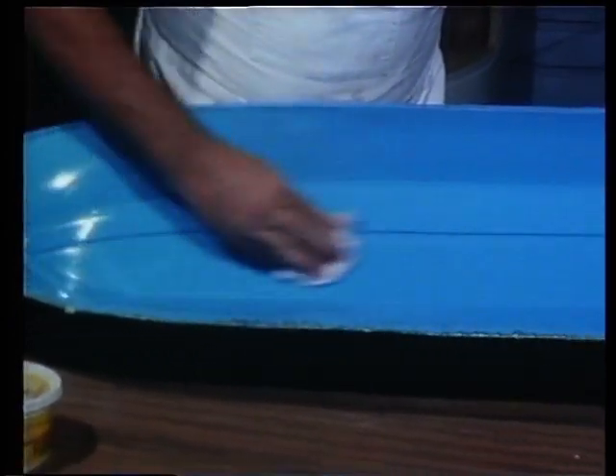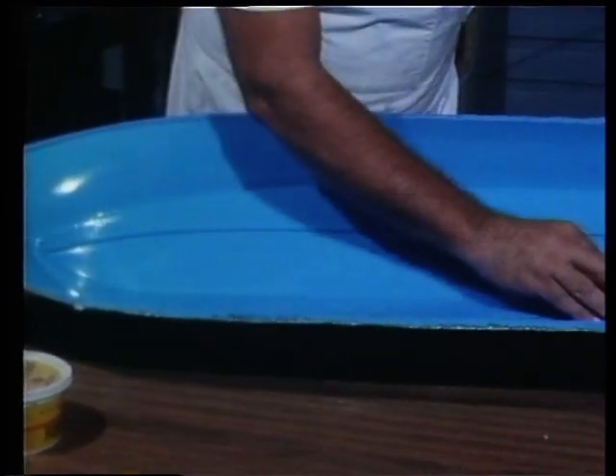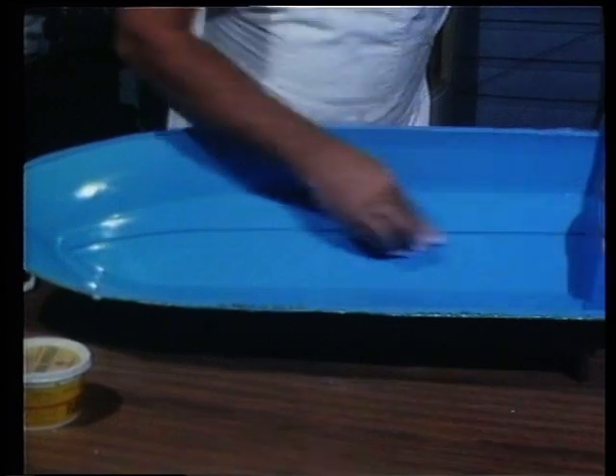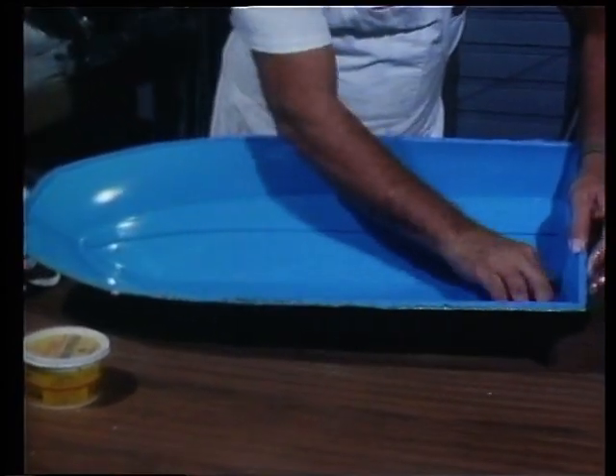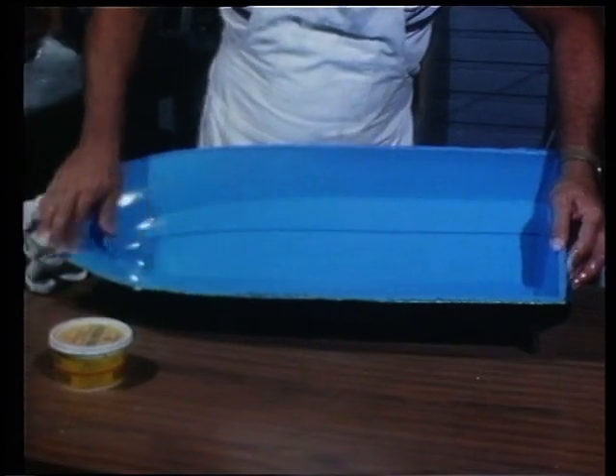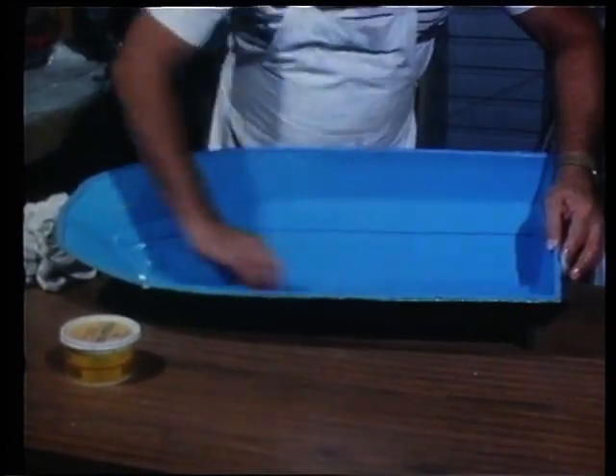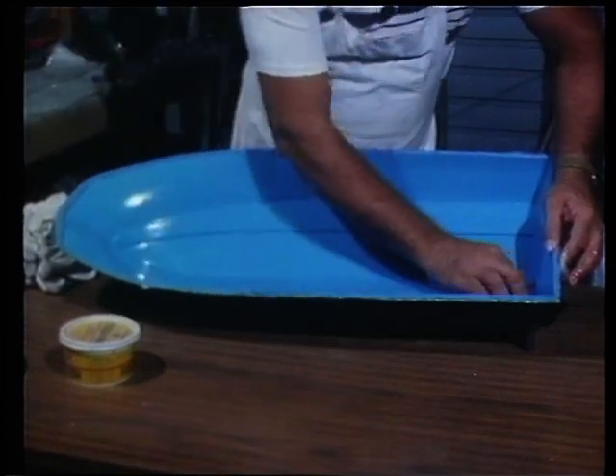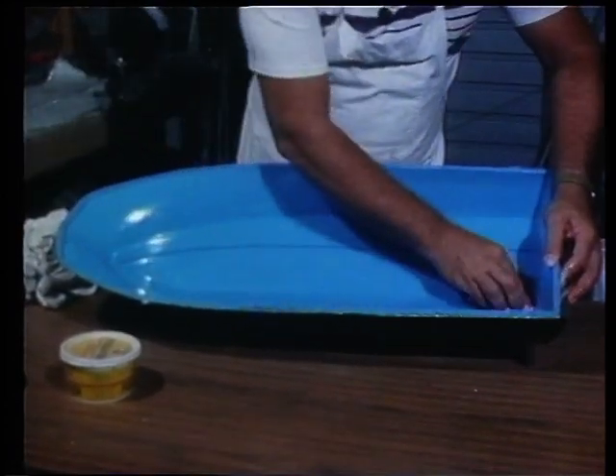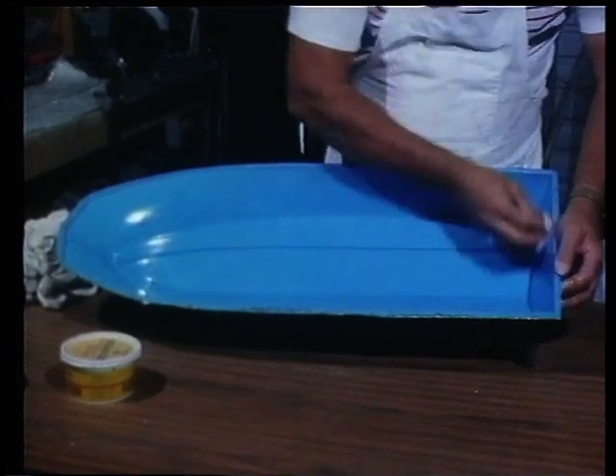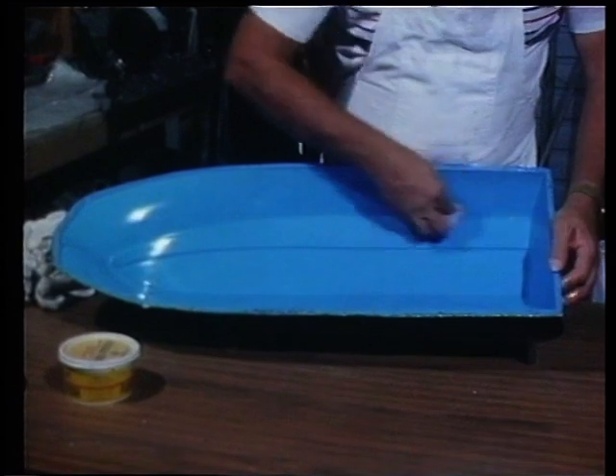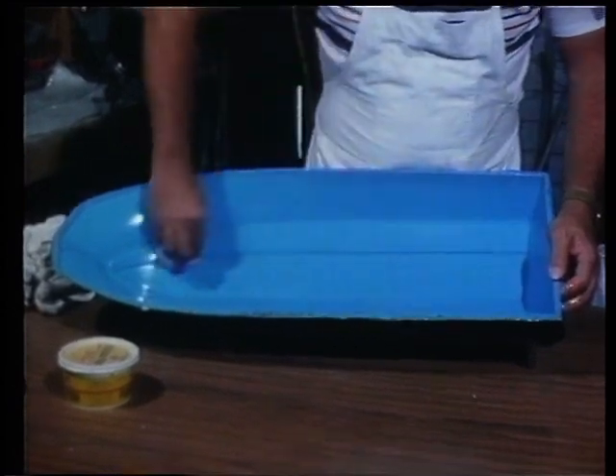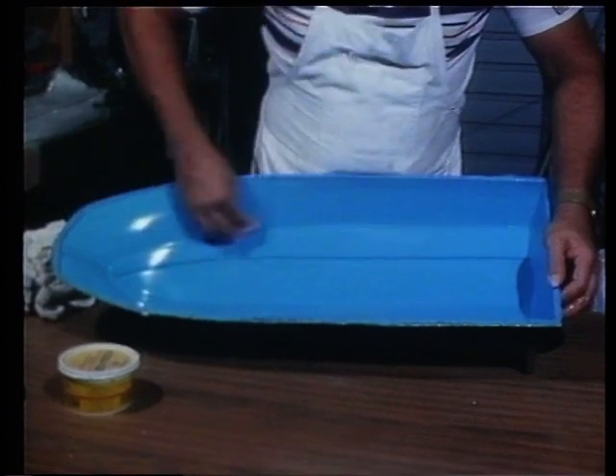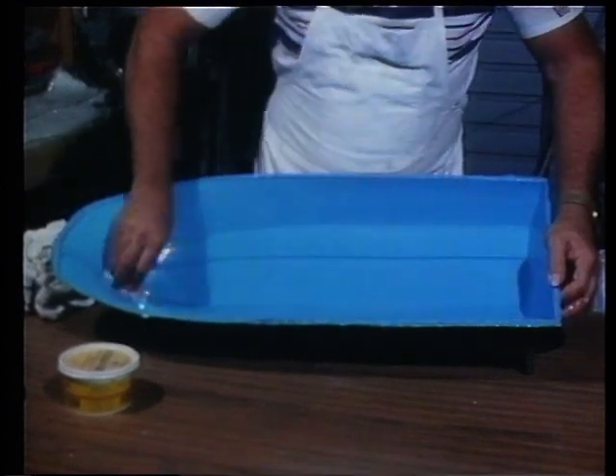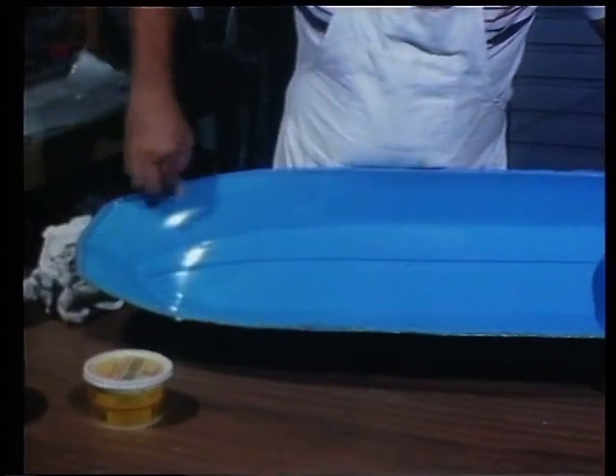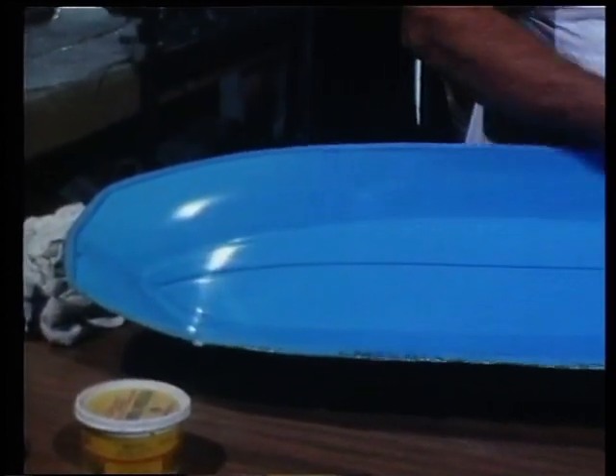Now the alternative for wiping the PVA in with the rag is to spray it with a spray gun. Again, it's probably beyond the scope of a lot of people who would be doing this on an amateur basis. Certainly not worth buying a spray gun specifically for that purpose when the rag does it perfectly. The only thing about it is you have to make sure that you cover 100% of the surface first time up, because you can't go back over it. Once that PVA dries, it's not possible to use the rag to wipe a second layer over. So as you can see, I'm being very thorough, making sure that my fingernail pushes that rag and therefore the release agent down into all of the little contours and the tight sections in the mould there.